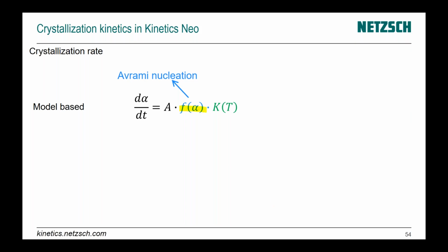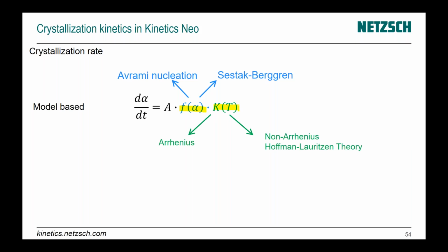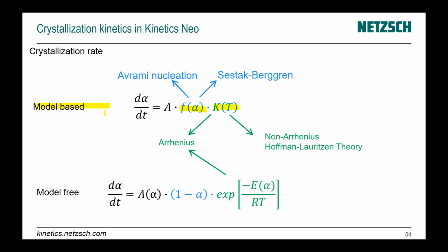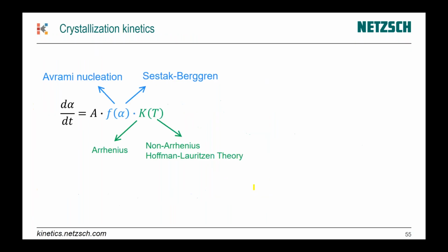This decreasing function could be different: f of alpha could be either Avrami or Sestak-Berggren for crystallization, and k, the function of temperature, could be either Arrhenius or non-Arrhenius. This is for model-based; for model-free, it is only the Arrhenius approach. Inside the software, we have all 4 combinations for crystallization.